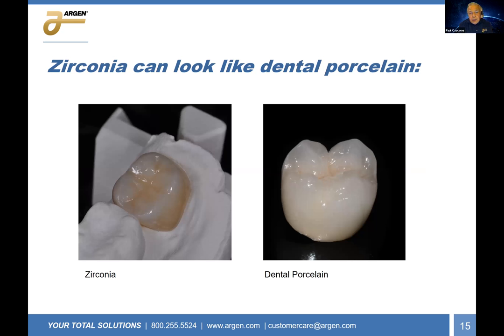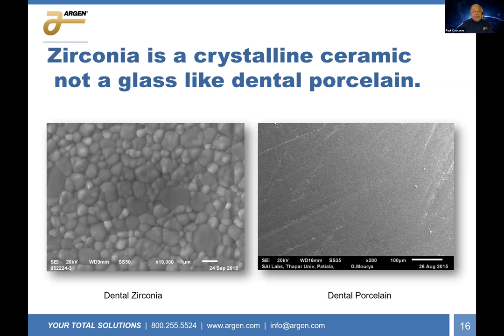Now it could look like dental porcelain. We have dental porcelain on the right and zirconia on the left, but that's on the outside. On the inside, it's extremely different. Zirconia is a crystalline ceramic, as you can see here. It has grains, has grain boundaries, just like an alloy does. A dental porcelain is a glass, has no structure whatsoever. So these differences make a very big difference in how the material can be handled, both in the laboratory and in the operatory.